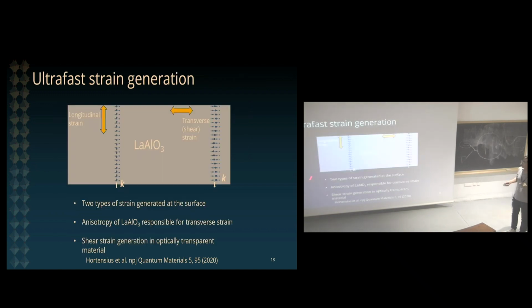Right. So that's a summary of what we see. When we excite phonons at resonance in perovskite materials, we typically generate an excitation of a coherent Raman mode that is oscillating around a displaced position. And we observe typically longitudinal strain waves, and in some materials we observe also a transverse or shear strain wave. Okay, so that's our starting point. So what can we do with this?